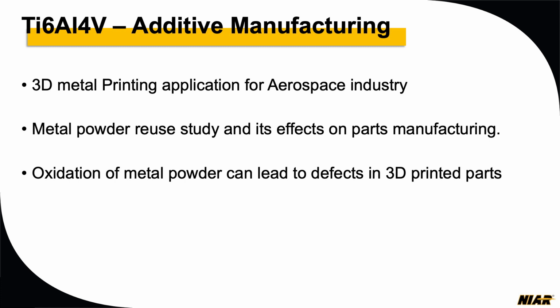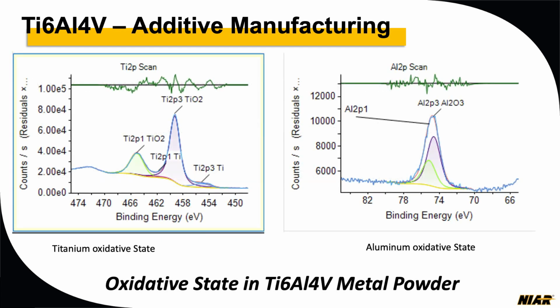So we analyzed the parts, and we were able to identify different titanium oxide and titanium metal. We were getting a good amount of titanium oxide all over, and again for aluminum oxide as well. So, less amount of aluminum metal.